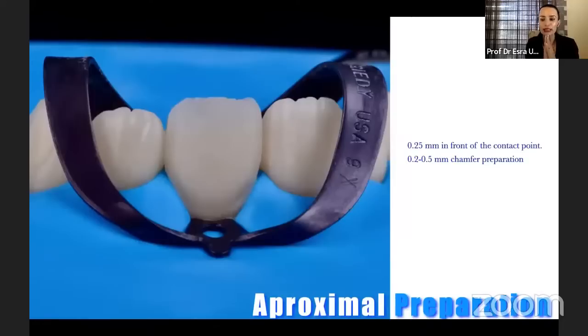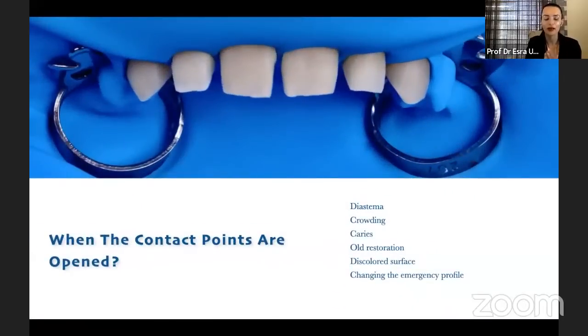Generally, we don't want to open the contact points, and the preparation should end 0.25 millimeter in front of the contact points, and 0.2 to 0.5 millimeter chamfer preparation is preferred for approximal preparation. But sometimes we have to open the contact points: for the rehabilitation of diastema, for diastema closure, if there's crowding, if there's caries on approximal surfaces, to remove old restorations and to mask the discolored surface, and also for changing the emergence profile. We open the contact points in those cases.